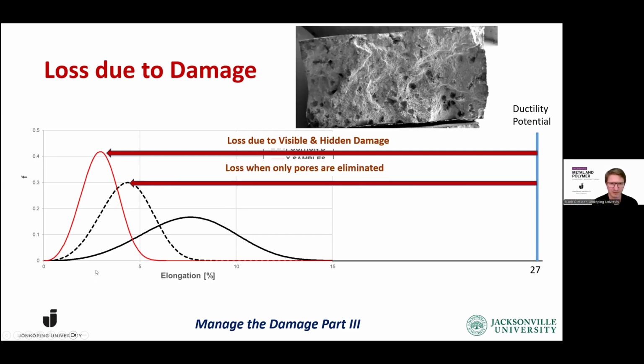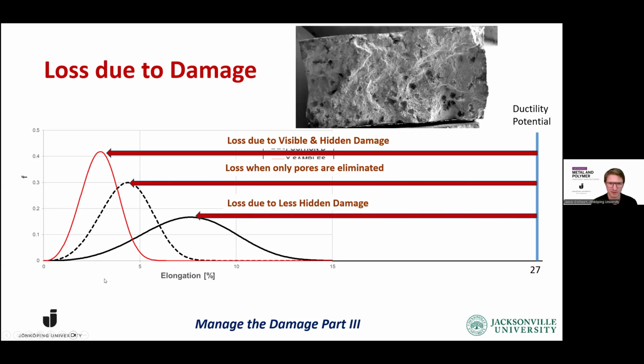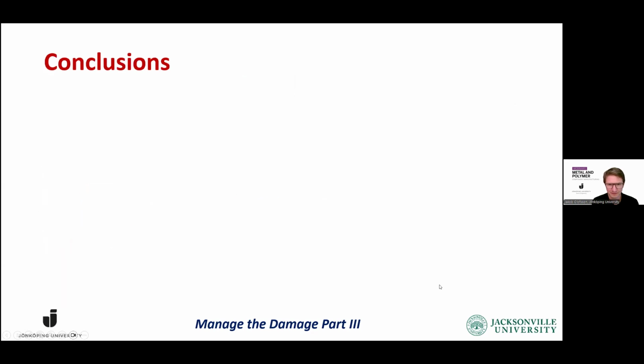If we focus on removing the pores, what do we get instead? Still, if we have the high level of hidden damage, it's not a really big gain that we get. But if we focus on lowering the hidden damage, we have a larger increase in elongation. We can see that there's a lot of fight to get onto the 27%, but focusing on reducing the hidden damage gives you more effect than removing just the porosity. So the visible damage does increase the effect of the hidden damage, but it doesn't remove the hidden damage. So battling only the pores, as we see it, is kind of misguided.